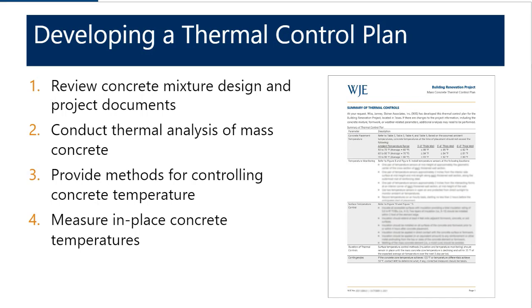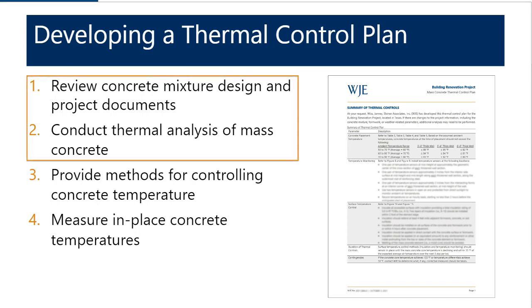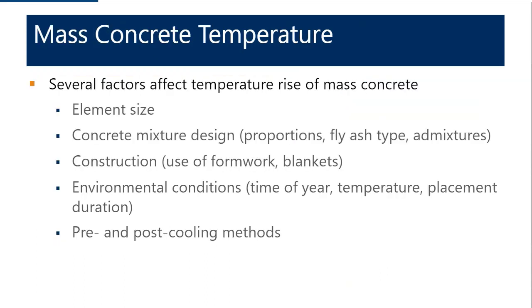We'll start with the first 2, which is reviewing the mix design and conducting the thermal analysis. So as we've talked about, mass concrete temperature is a function of several factors, including the element size, the concrete mixture design, construction methods such as the use of formwork or insulating blankets that might help trap heat in the placement, environmental conditions, so the time of the year.